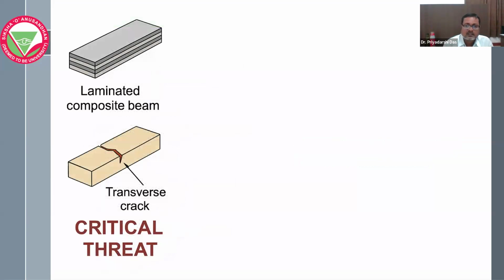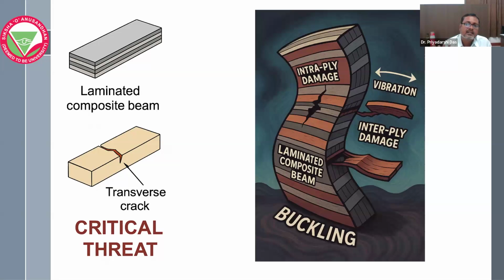Like I said, if a structure is continuously used or widely engaged in such engineering fields, it has the tendency to form cracks or disintegrations. When formed inside the structure, the disintegration will lead to catastrophic failure. On wide engagement, the structure will combinedly attract vibration and loading. If vibration, loading, and buckling happen at the same time, then both intra-ply failure and inter-ply failure will happen. This will damage the structure very quickly, so on both vibration and buckling, the catastrophic failure will occur sooner rather than later.